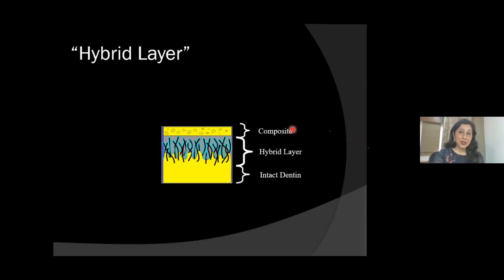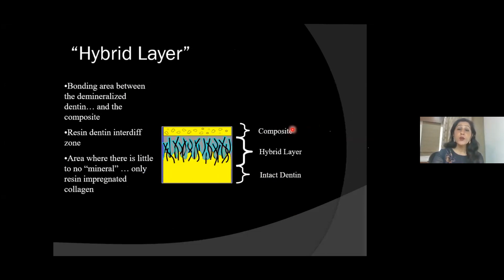And you have to form this. This is the hybrid layer which you have to form when you do a good etching and bonding. And when you use self-etch, you also have to form this hybrid layer, which is the layer between the composite and the intact dentine. This is the bonding area between the demineralized dentine and the composite, where there is only very little or no mineral and only resin-impregnated collagen, because we saw the collagen noodles floating and we also saw the bonding agent, the adhesives, the primers getting into the collagen, making it resin infiltrated and making it strong. And this is what is called the hybrid layer.